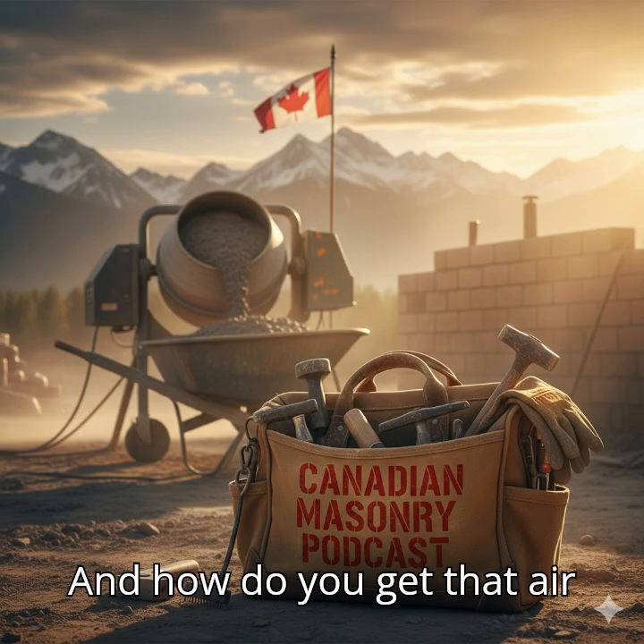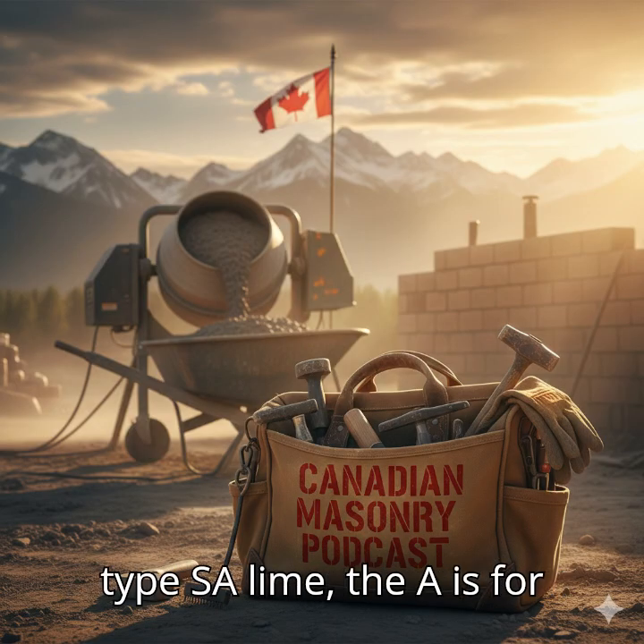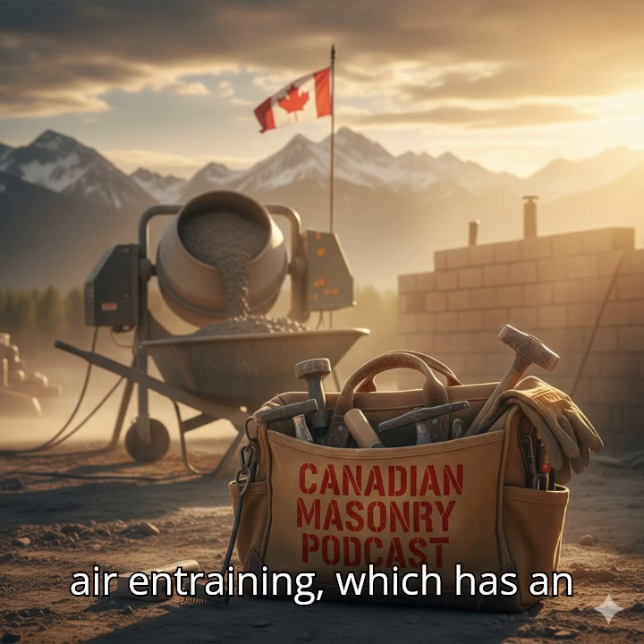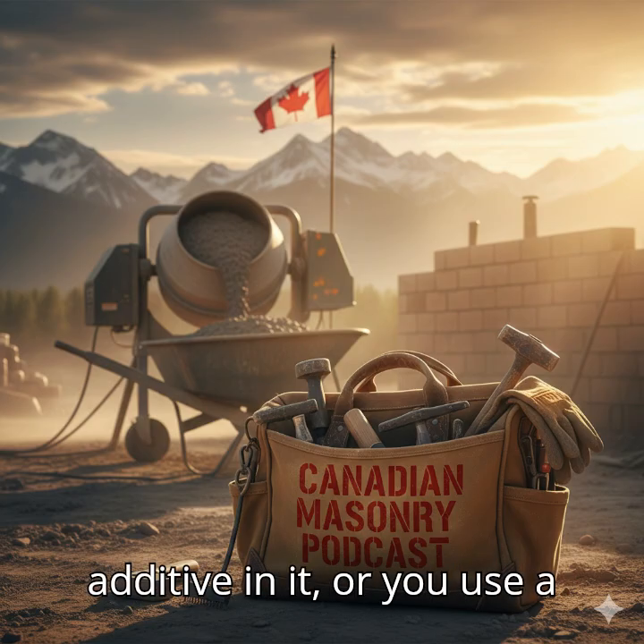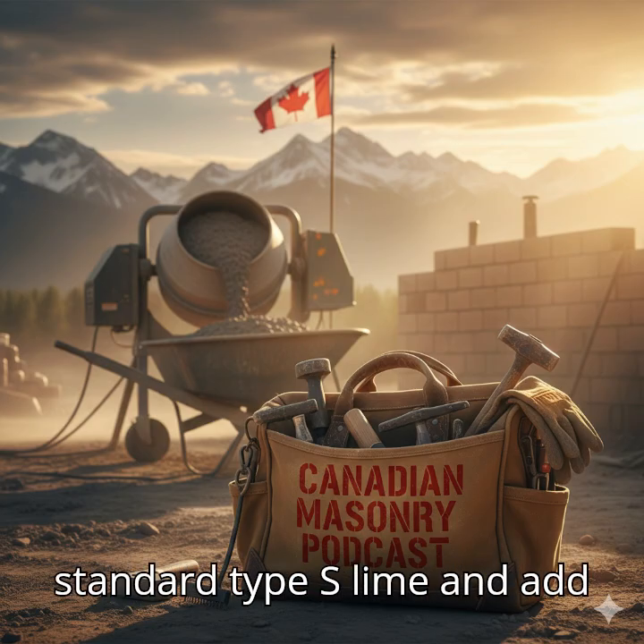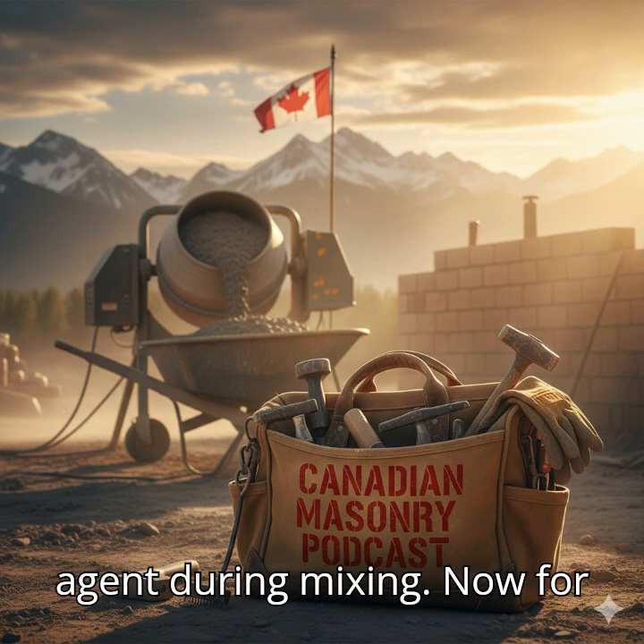And how do you get that air in there? You either use a type SA lime, the A is for air entraining, which has an additive in it, or you use a standard type S lime and add a specific air entraining agent during mixing.